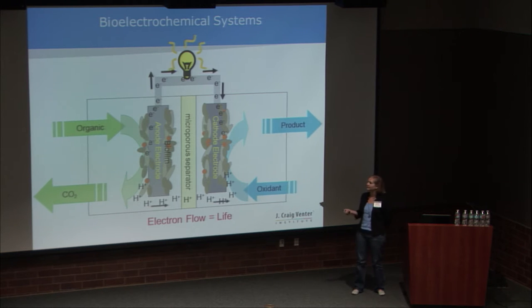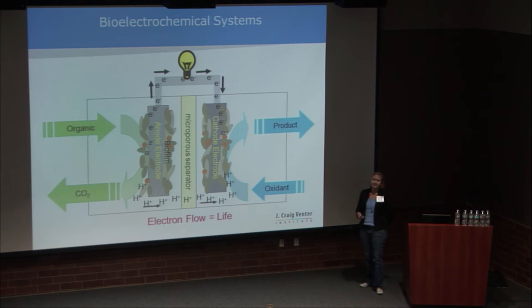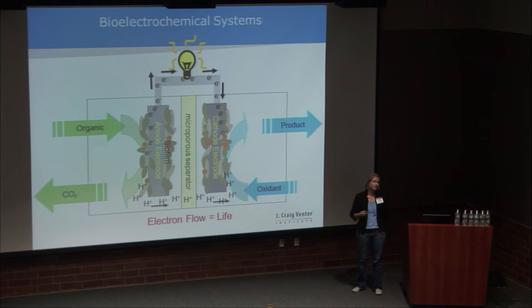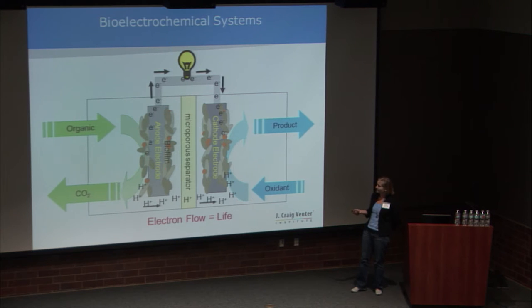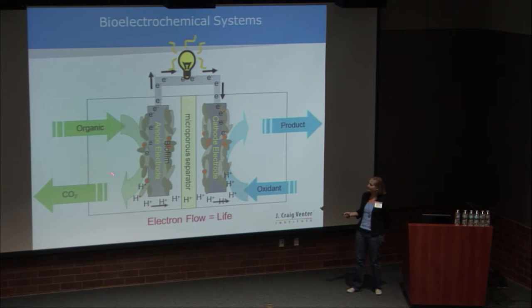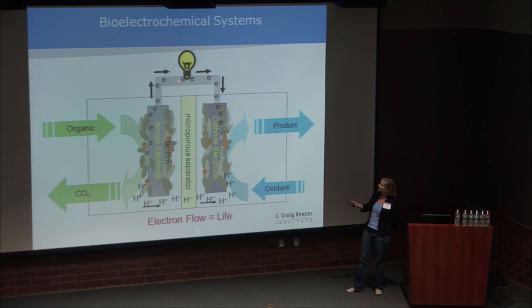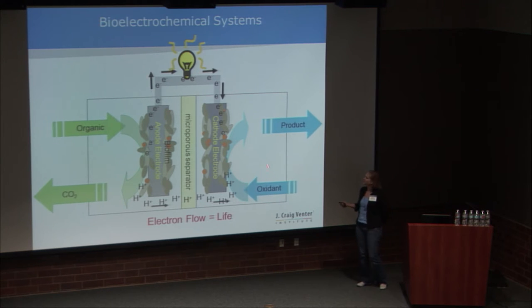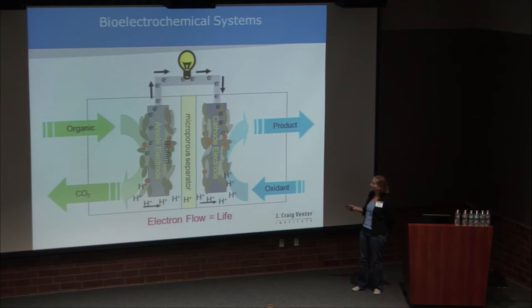Typically we use graphite or carbon as our electrode material — it's very stable at neutral pH and standard temperatures, it can accept a lot of electrons, and we can mold it into many different configurations to optimize the amount of biofilm on our surface. Our bugs stick onto the electrodes, oxidize the organics ultimately to carbon dioxide. Protons are transferred internally through the system, and electrons are conducted across an external circuit, producing direct electricity. Those electrons and protons recombine at the cathode compartment.